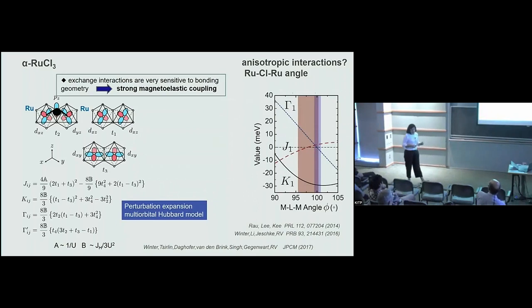Now, what one can observe already from this perturbation expansion is that very small changes in these hybridizations, that one can quantitatively define in terms of this angle that I'm plotting here, make huge changes in your exchange interactions. So for instance, if you put the information of these hopping parameters for alpha ruthenium trichloride, by distorting this angle a little bit, one can get that these non-Kitaev terms, so this is the off-diagonal gamma terms, and this is the Heisenberg term, you may be able to suppress them and bring the system into a more pure Kitaev. So what we see is that in all these Kitaev candidate materials, the magnetoelastic coupling is very strong.